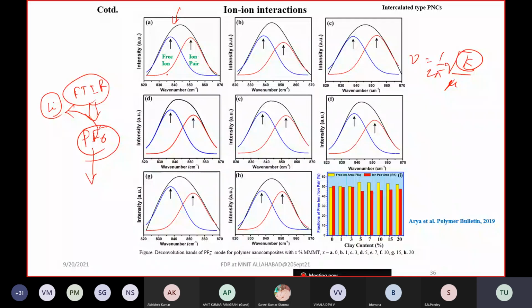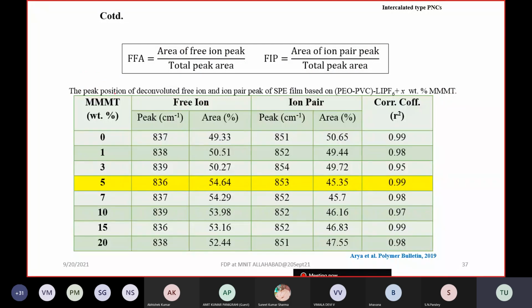So if you are adding the clay into it, then this free ion is going to start improving. This improvement is going to be judged by a formula. You can consider that the fraction of free anion is going to be calculated using the area of the free ion peak upon the total peak area, and the ion pair is going to be calculated as the area of the ion pair peak over the total peak area. So you can consider from here that this concentration is going to give you the best results, where the ion pair to free ion ratio is good.